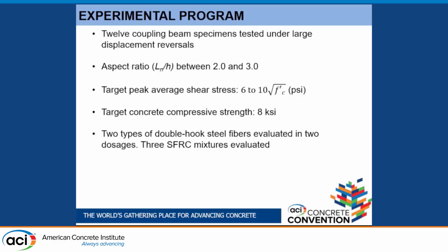So we tested 12 coupling beams. They were large scale, as I will show, with large displacement reversals. We looked at different aspect ratios ranging between 2 and 3 to cover the typical range, with shear stresses between 6 and 10 - remember, 10 is the upper limit for a diagonally reinforced concrete coupling beam - in terms of square root of f prime c in PSI. We targeted a compressive strength for the concrete of 8,000 PSI.